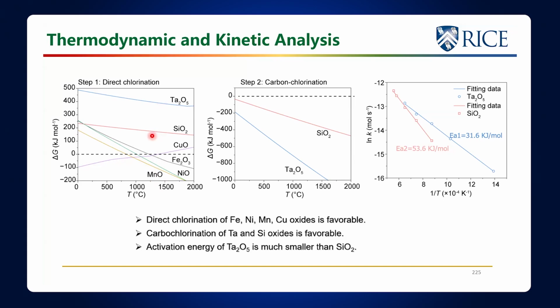Silicon and tantalum are not going to react with chlorine at any temperature. However, if you do the carbochlorination, so now you add the carbon to it to reduce these, then the reactions can go. So if you do a carbochlorination, both of them are going to be spontaneous over the entire temperature range. So how are you going to separate them?